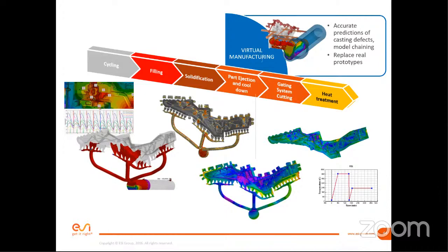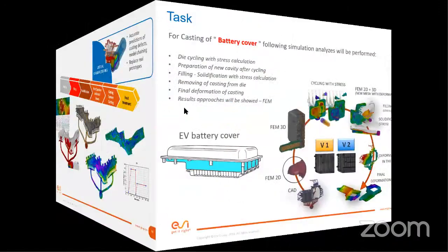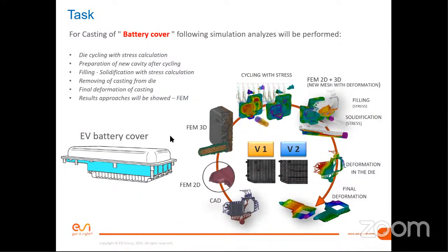And again, this slide shows that we actually are able to do it, so we can introduce the cycling phase, filling, solidification, then ejection, and cool down. And even the influence of what happened with the residual stresses and how the casting will deform after the cutting of the gating system and heat treatment, for example. This is just an example which really takes into account all the case. But let me use another case to show the most advanced approach for the simulation of high-pressure die casting technology.